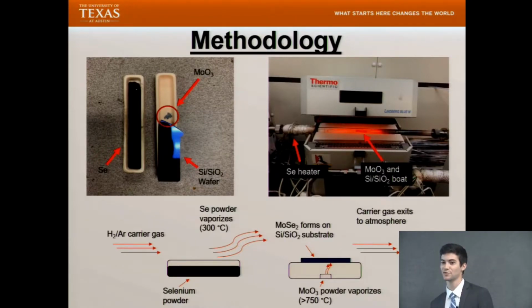So to create my samples, I started by loading selenium powder and molybdenum oxide powder into two separate ceramic boats, as you can see right here. I then placed a silicon oxide wafer on the molybdenum oxide boat and loaded it into the center of the furnace. Next, I loaded the selenium boat into the same tube, but just outside of the furnace, as it has its own heater. Then I heated up the furnace, vaporized these precursors, and they would react to form molybdenum diselenide on my silicon-based wafer. Then finally, I cooled the furnace and removed the sample for characterization.